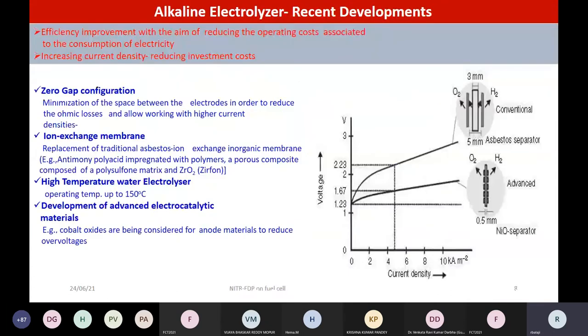So in order to overcome these issues, there are approaches currently being adopted to minimize the losses as well as to increase the efficiency of the system. There is a zero gap configuration, similar to the polymer electrolyte membrane based technology, where people are now working on developing an alkaline OH minus ion conducting membrane based electrolysis system, so that you can considerably reduce the inter-electrode distance. If you take any electrochemical system, as long as you reduce the inter-electrode distance between anode and cathode, you can considerably reduce the voltage loss. That is the basic concept of any electrochemical system. So when you adopt this kind of membrane-based technology, you can considerably reduce the inter-electrode distance between anode and cathode. That will reflect in saving in voltage loss, and thus in energy loss.